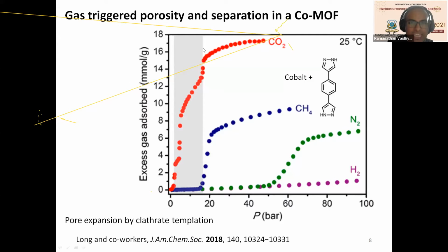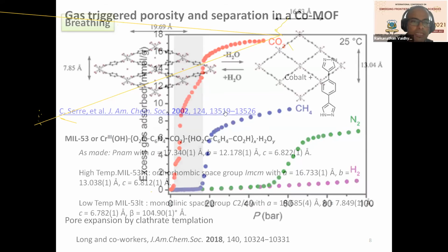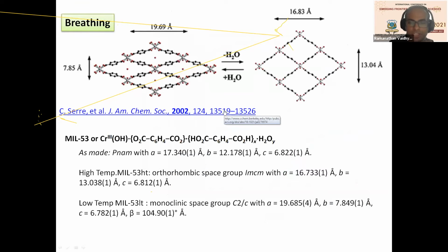All right. So this gray area represents the area where you can achieve high separation of CO2 over methane. But the beauty of this thing is, look at how the structural change in a very solid material like a MOF is caused by a gas at a high pressure. But look at the pressures, about 18 bars. That's where the methane is able to cause a structural change. This is a very good example of why these structural changes can become very important when it comes to achieving high selectivity for a specific gas over other gases. Now, what is the structural change that we are talking about?